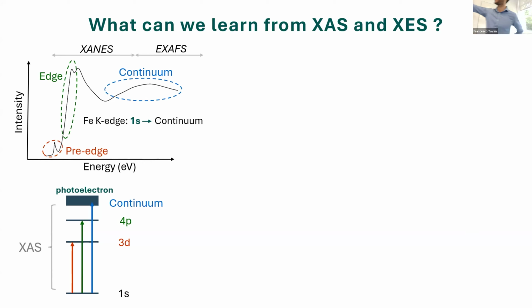You have two regions, XANES, which goes from about 0 to 100 eV starting from the main absorption edge, and then the EXAFS region. In the XANES, we can also have these very sharp, lower intensity peaks. These are called pre-edge transitions, and in the case of the K edge, they are due to transitions of the 1s electron into bound states, for example 3d orbitals, and these are very sensitive to spin and oxidation state of the given photoabsorber.